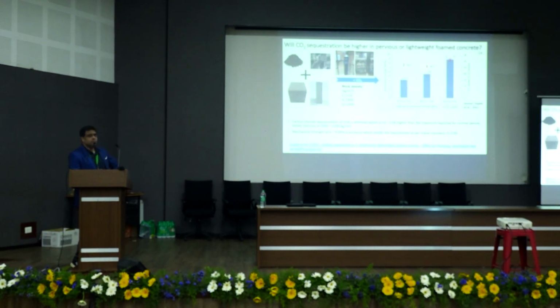But what about the engineering properties? Well, we made blocks of three different densities, 1,150, 1,300, and 1,450 kg per meter cube, which is about 50% to 60, 65% of the normal mortar density. And we find that the total CO2 uptake can be as high as 31%, depending on the density, right? And the strength that we get varies in the range of 4 to 9 megapascal, which satisfies what is needed for making blocks for building and other infrastructure purposes.